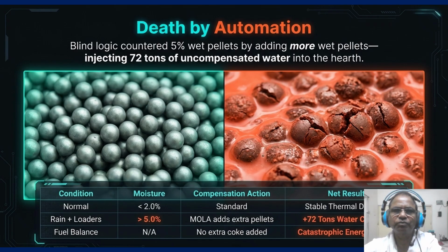Pellet moisture jumped from under 2% to over 5%. Here is the death by automation. The MOLA system saw the moisture and maintained the mass balance. It added more wet pellets. It injected 72 tons of uncompensated liquid water directly into the hearth.